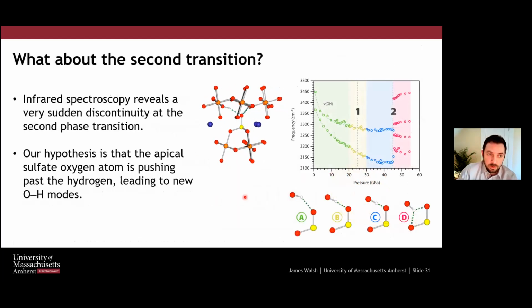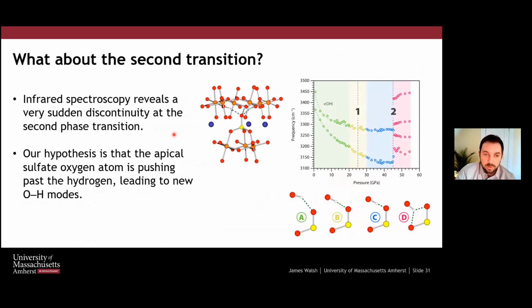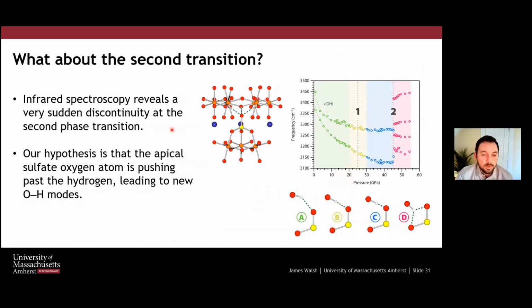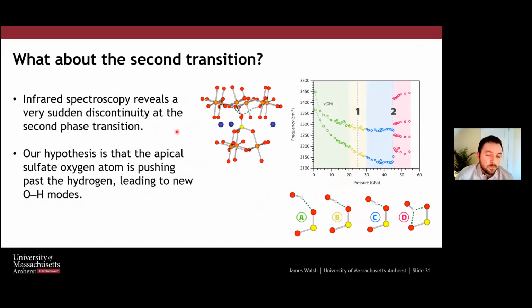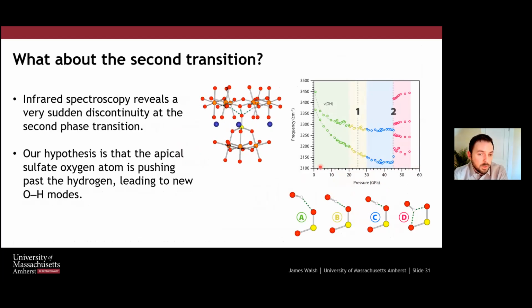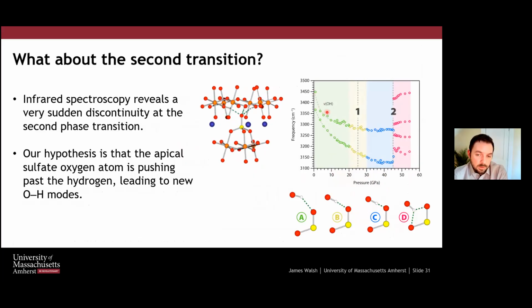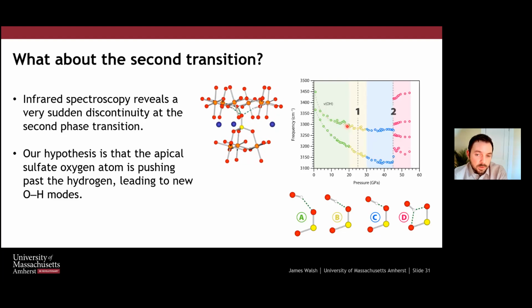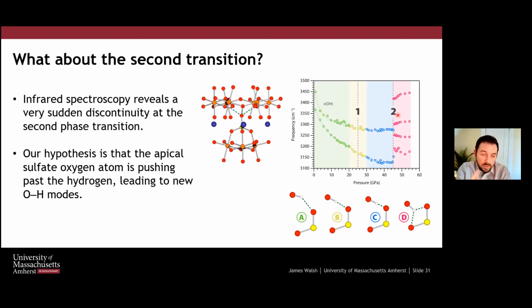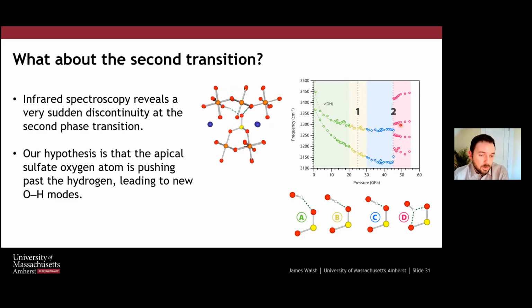So what about the second transition? To figure this out, we ended up having to use infrared spectroscopy. This was work done with Zhenzhen Liu at NSLS-II. We performed infrared spectroscopy over the pressure range up to around 60 GPa. And what we see there, our hypothesis, is that we have these four regions where initially we have these two hydrogen modes, oxygen-hydrogen OH modes, that decrease in frequency and then start to stiffen at these pressures, becoming almost linear in this region. And then right at the same pressure that we see in the X-ray diffraction this second phase transition, we see an abrupt discontinuity in the infrared.